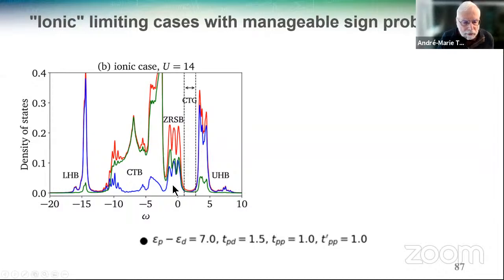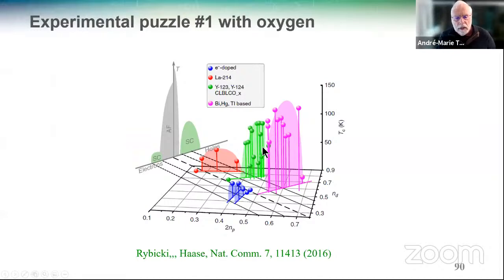And this is the so-called Zhang-Rice singlet band that I will describe in a little bit more detail. And that's the charge transfer band. And that's what I will call the charge transfer gap. It will play an important role in a second. Okay. So the experimental result I want to look at here is an experimental puzzle that's been around for a long time with oxygen. So this paper is 2016, but in fact, it takes data from basically the beginning of the high-TC field. So there are different families here. There's the lanthanum family, and there's the bismuth, mercury, thallium type, and this height here is TC, and these are the YBCO compounds.